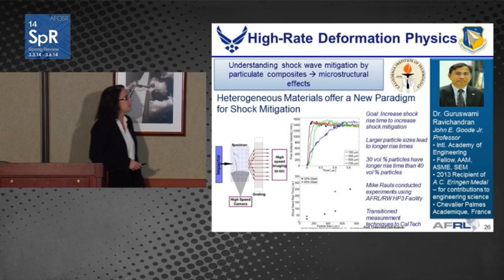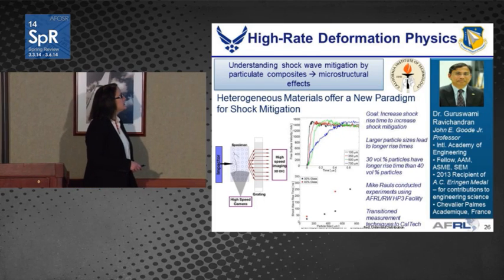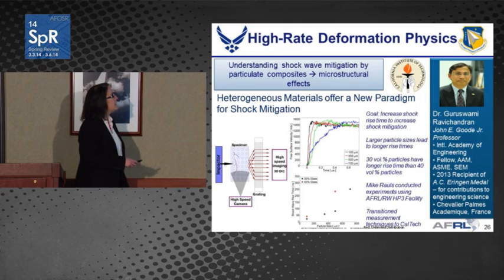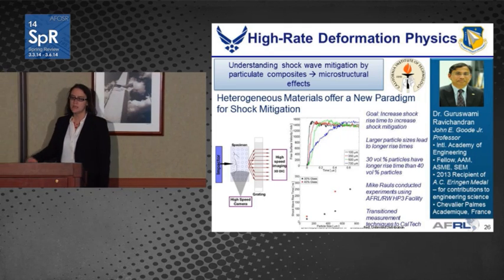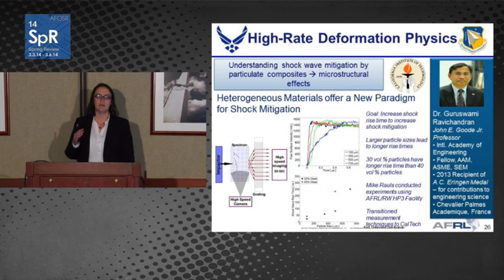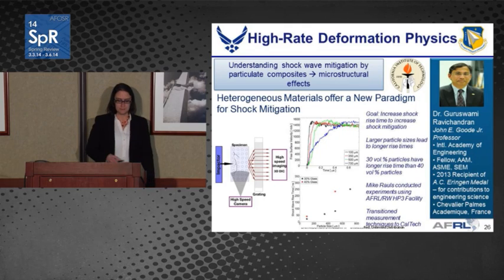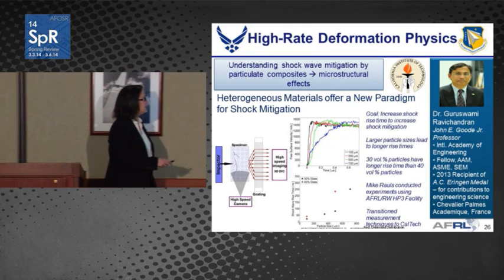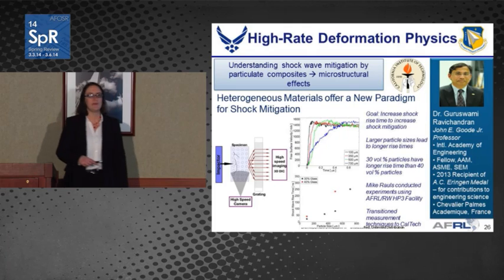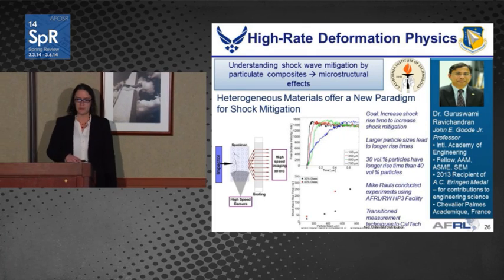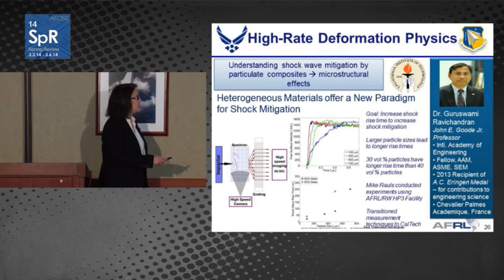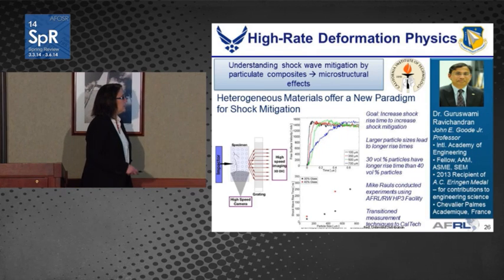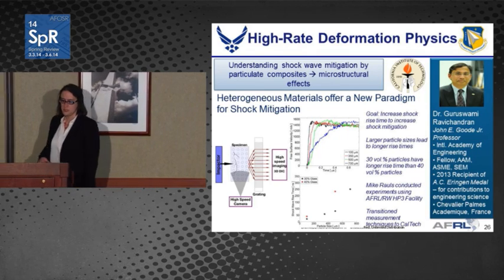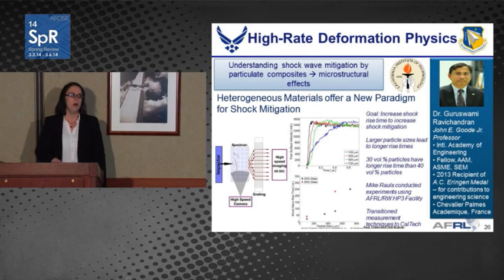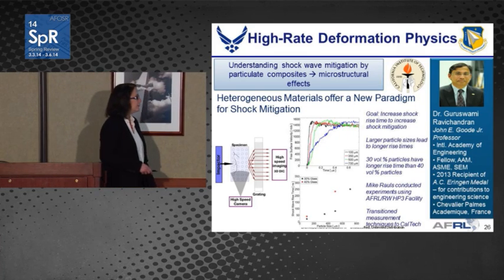So this is work in Dr. Ravichandran's lab at Caltech, where he's looking at trying to understand how the shock wave is mitigated by particulate composites by changing the microstructure of the composite, in this case the volume fraction and the particle size. And so what they're doing is they're impacting these materials that have glass, I think they're glass beads in a PMMA matrix with varying particle sizes and volume fractions, and they're measuring the free surface velocity off of these materials. The free surface velocity is an indicator of the pressure or the shock velocity in the material.